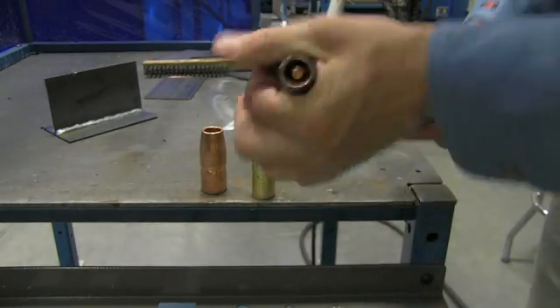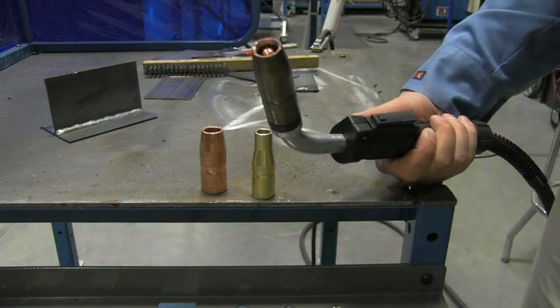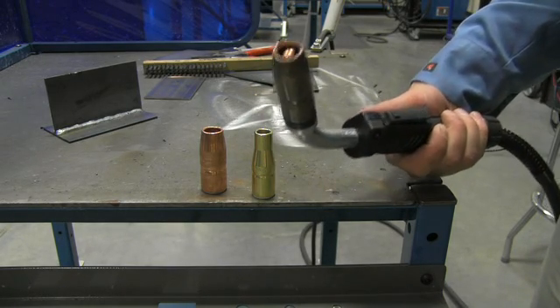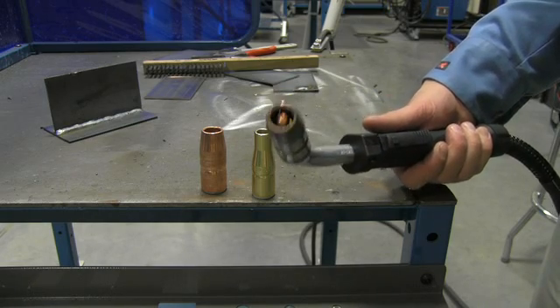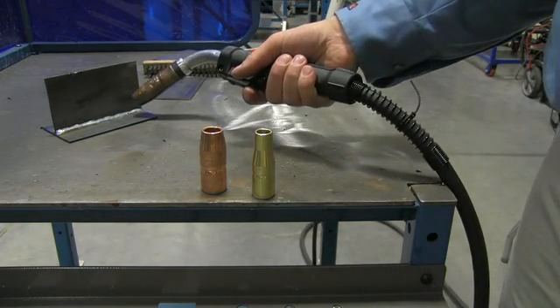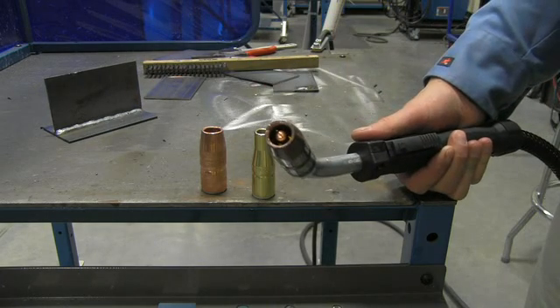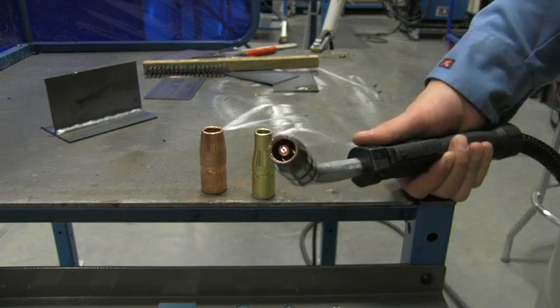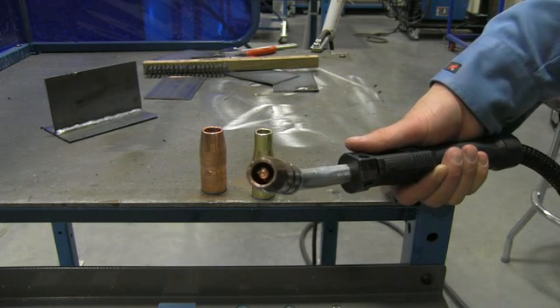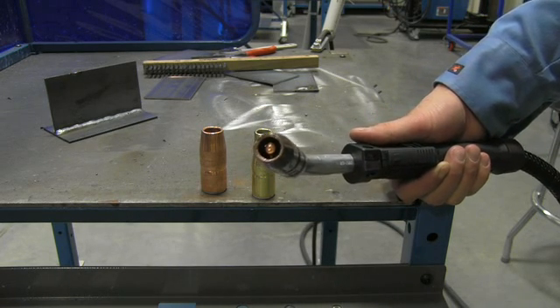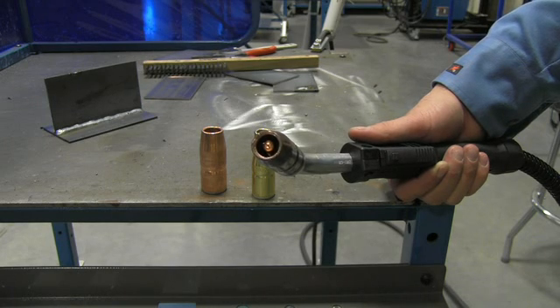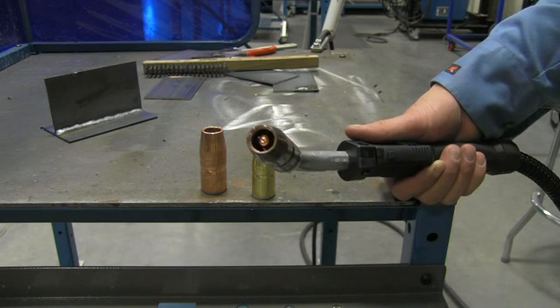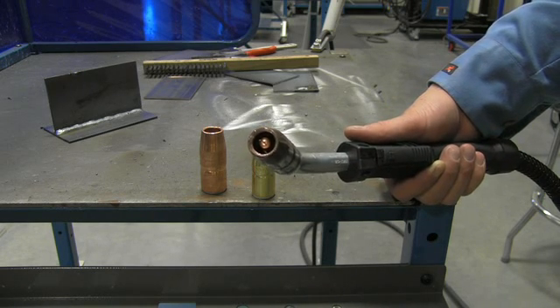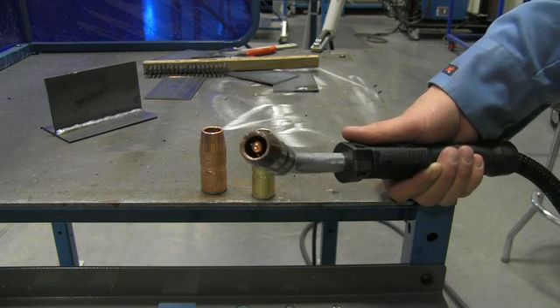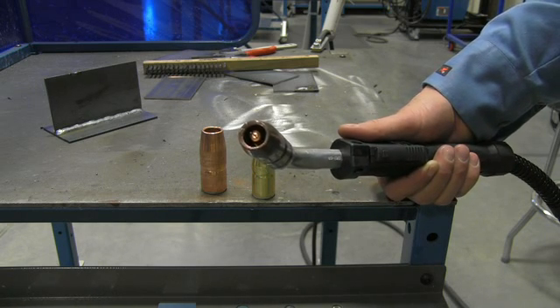Now for spray transfer, we would want our contact tip to be recessed in 1/8 inch. This protects the contact tip from the higher heat process, okay, and also allows us to more easily maintain that 1/2 to 3/4 inch stickout without sacrificing gas coverage, because we can still stay a little bit closer, but our contact tip is sucked back in the nozzle. So if you were to try to short circuit weld with this, what you would probably see is the guys welding with a longer stickout than recommended, and so that's going to produce some very spattery starts, lower welding currents and lower voltages, which may lead to lack of fusion. So keep this in mind when you're setting up the welding process for short circuit transfer, that you maintain the appropriate 1/4 to 3/8 inch of electrode extension.